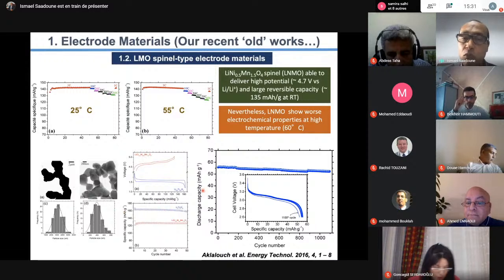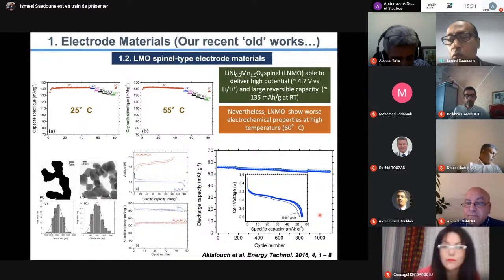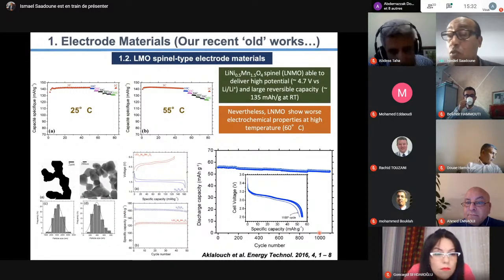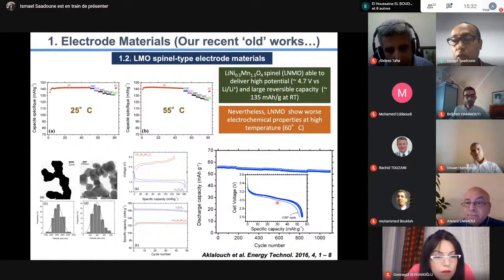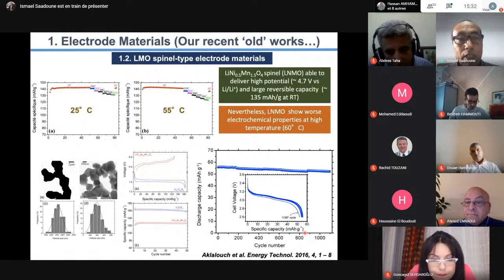And you see we succeeded in getting almost more than 1,000 cycles - too much from the lab, okay? And we have this voltage profile. This was also published, unfortunately, in Energy Technology, but we should keep in mind that we could have patented our results - but it's too late now.